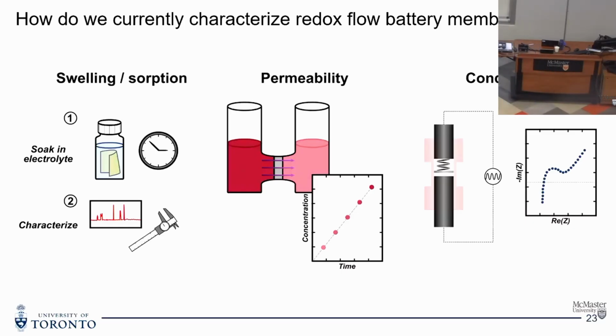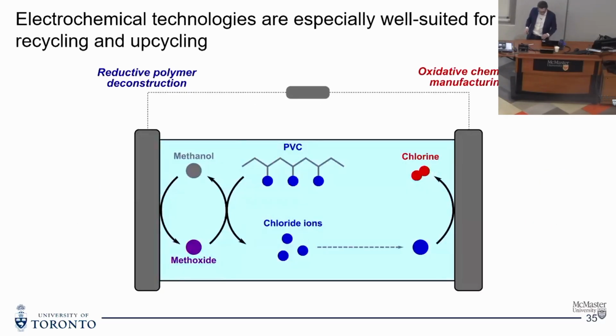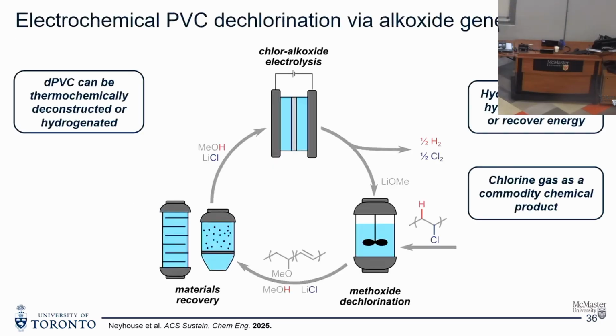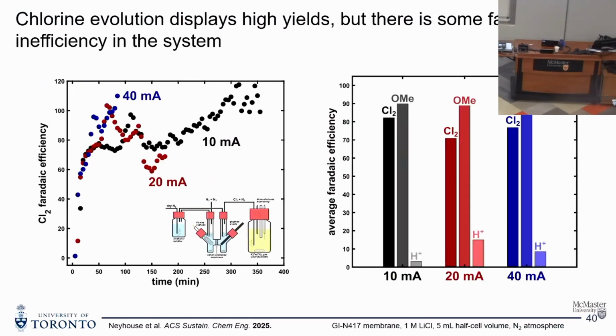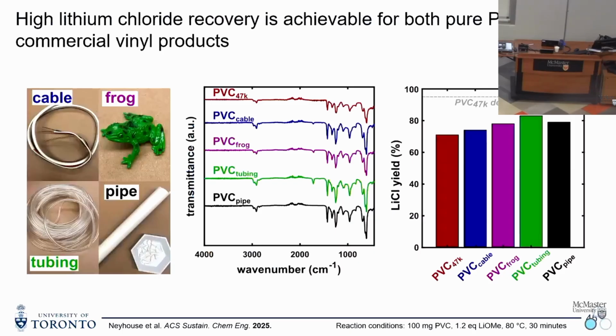Thanks for the talk. Those soft PVC toys for kids are, of course, filled with phthalates. I'm wondering what's going on with the phthalates there. Are they also getting reduced? Yeah, so almost. What we did when we actually did these experiments, I wish I had my backup slide on this, is we extracted out the PVC first. So we separated out the phthalates. We wanted to be able to quantify the lithium chloride yield, so we need to know exactly how much PVC went in. But if you take phthalates and react them with lithium methoxide, you're going to get methanolysis. It would be base mediated, but you would only lose a methanol and not a base. So you would end up with a methyl ester, and that's something we've recovered and quantified.